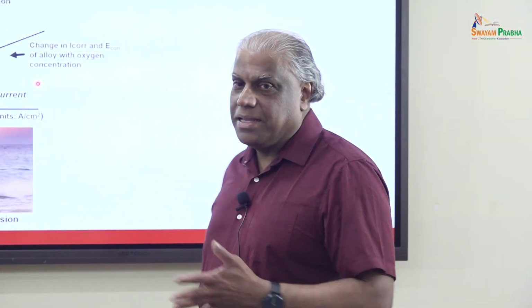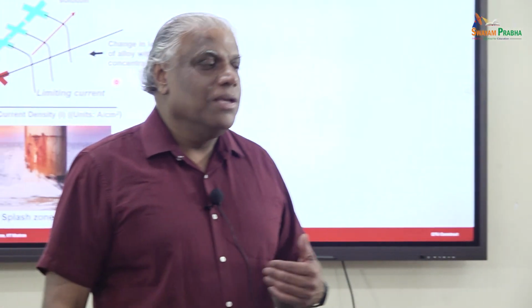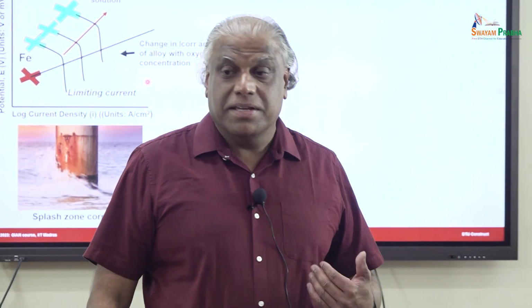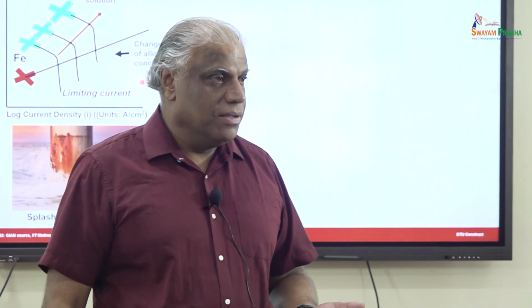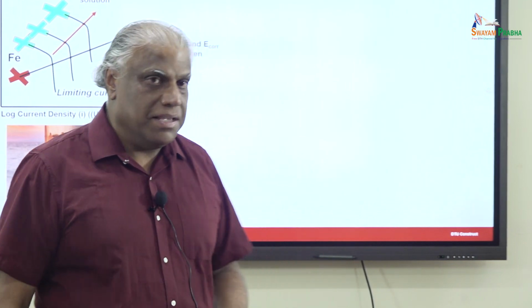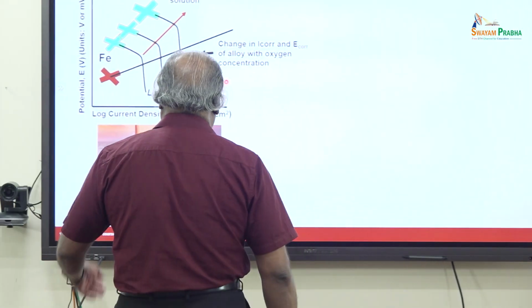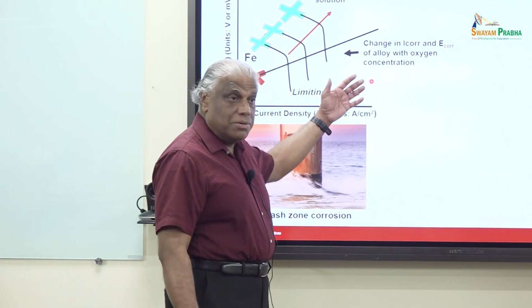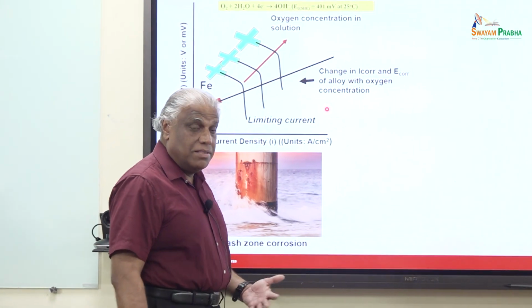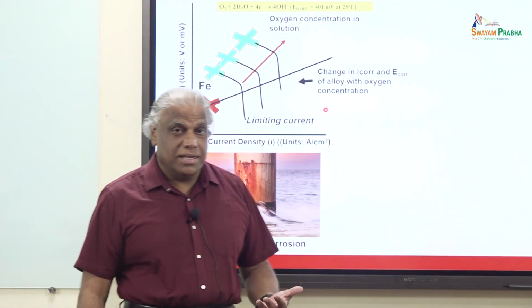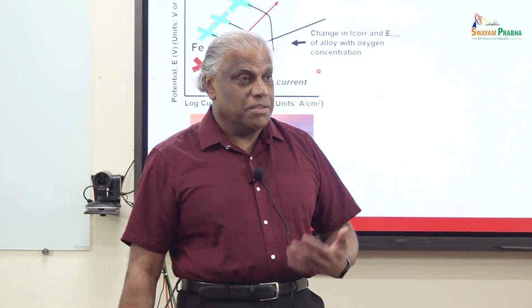Agitation. If you have stirring in the solutions, you can increase the flow. You can increase the temperature. If you increase the temperature, diffusion will be faster. So all these parameters will increase the oxygen diffusion, and that way you will have more shift, right? You can see that in actual practice. This is exactly, again, if there is oxygen in the oil and gas condition, this is a problem, because